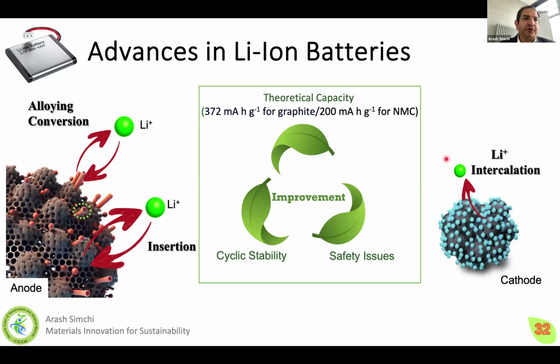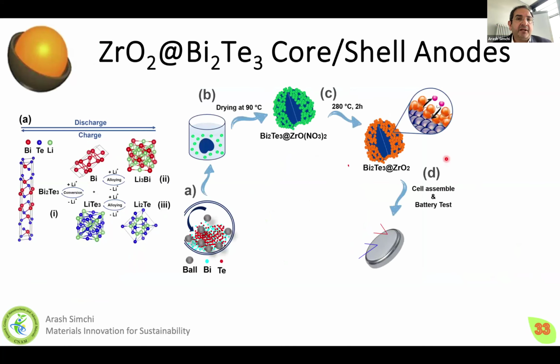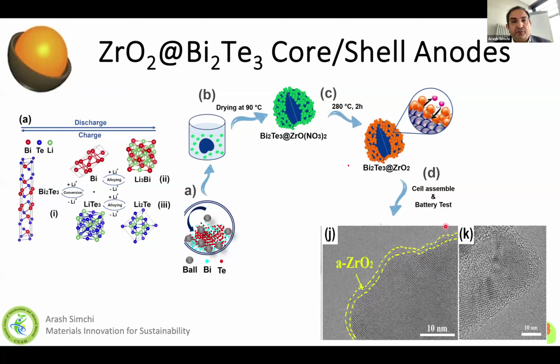So we work in our group quite a lot on lithium-ion batteries, how to make efficient batteries with high stability. I just want to show you one of our recent examples. We use bismuth telluride as a core and coat it with a thin layer of zirconium oxide, a 2 nanometer amorphous material, by a simple chemical process. This is a very good example of how we can avoid very expensive materials and go back to chemistry, using current materials which we use in the laboratory with simple chemical processes. As you see here, we just mix our bismuth telluride with a precursor of zirconium and then heat it at a low temperature, 280, and create a very thin layer of amorphous zirconium oxide.